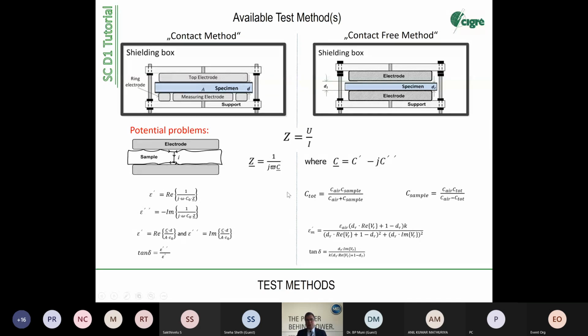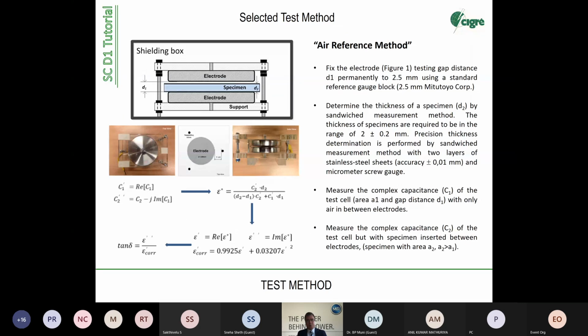Yeah, the contact-free method is also called the air reference method. You take a reference without a specimen, and then in the same arrangement you take a measurement with a specimen, and from this, from the theory behind, you calculate the complex capacitance. What was done here? We worked normally with the electrode fixed at a distance of 2.5 millimeter.